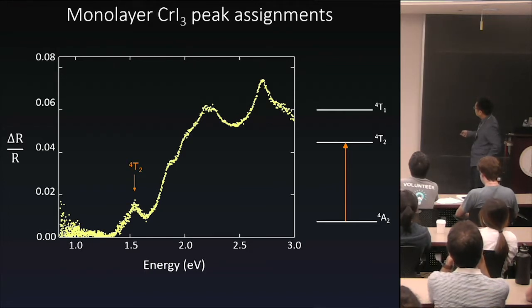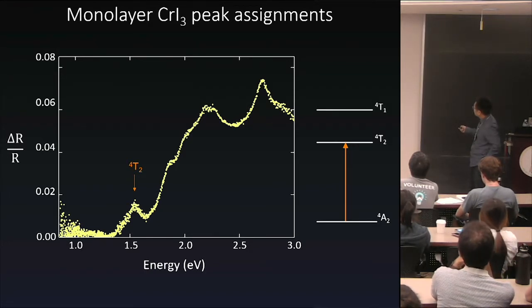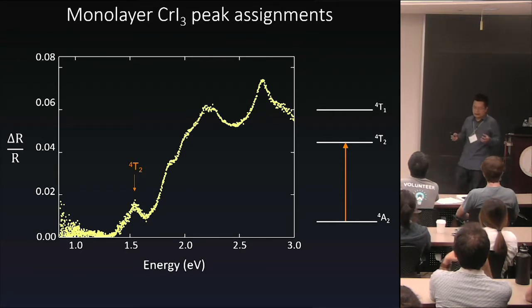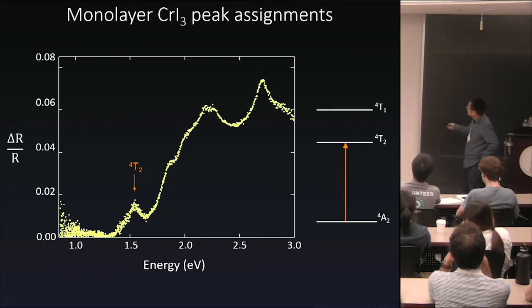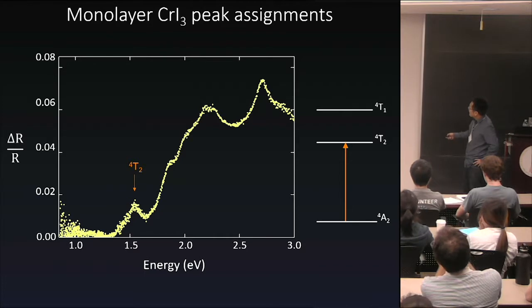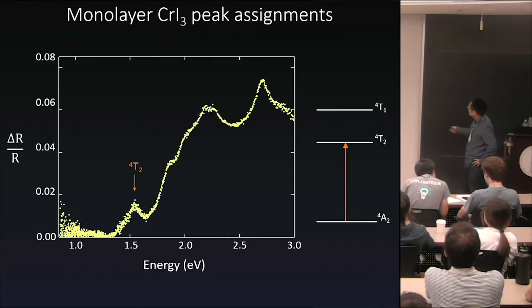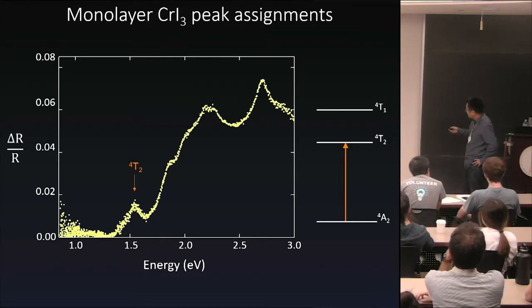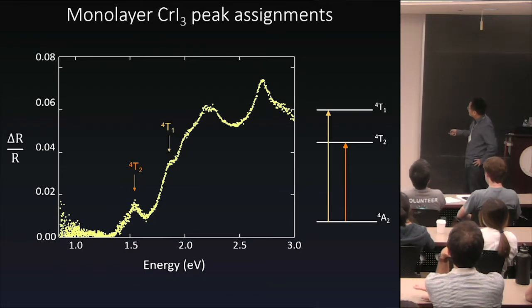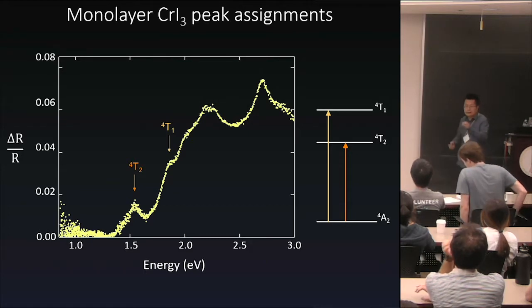The ground state is 4A2. Then there's a 4T2 and a 4T1. The A and the T represent the irreducible representations, the group basically. Here what I show you is the reflection measurements from the samples, and you can see there are about 4 peaks. The lowest energy one is coming from the transition I show you here, from 4A2 to 4T2. Then there's another one, from 4A2 to 4T1. Both of them are coming from these D to D transitions.